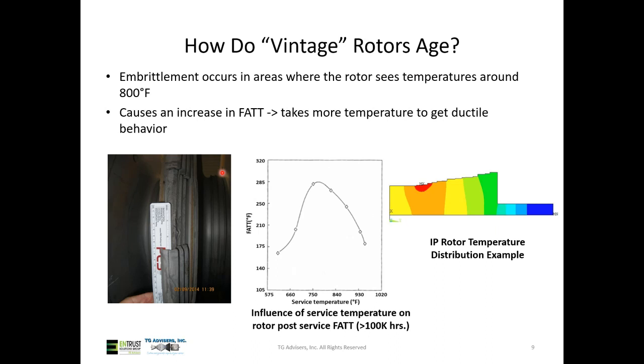I alluded to just a minute ago that a phenomenon called embrittlement occurs, and it happens around an operating temperature of roughly 800 degrees. That's where we see peak embrittlement. And to not get too technical, essentially what it does is it heat treats that rotor over time, and it just requires more temperature or a higher temperature with time to get to the point that we're getting that good ductility again. So what we have on the left side, this was a high temperature rotor with over 400,000 hours. And you could see that it became so brittle that the serrations or the lugs just peeled right off the rotor from embrittlement.